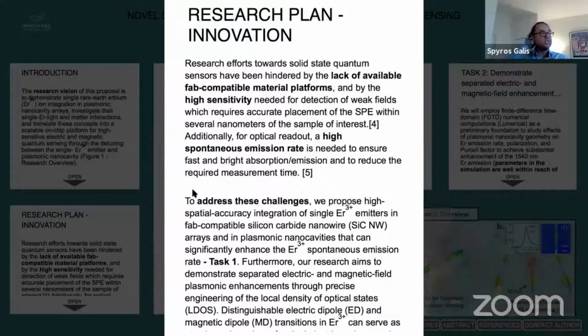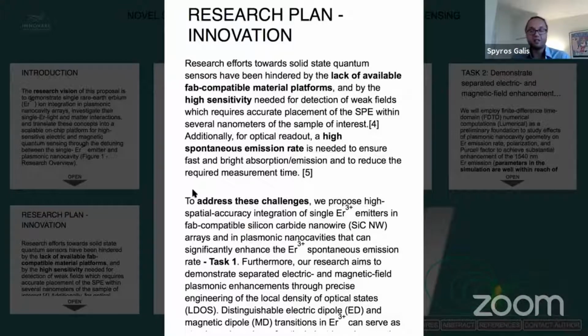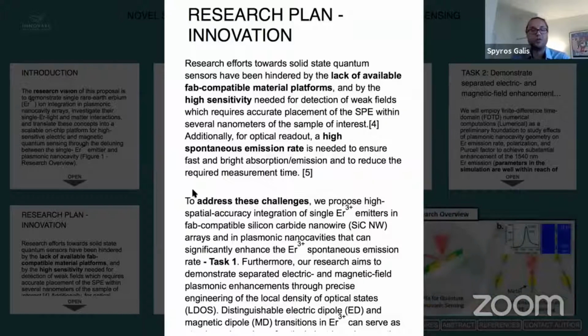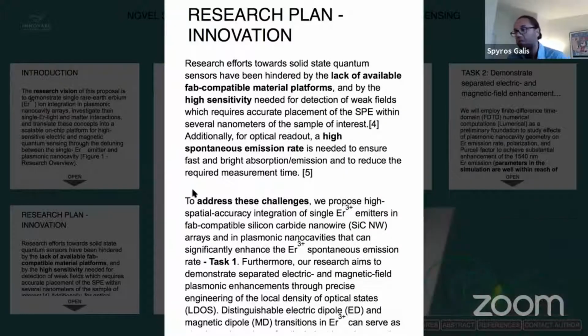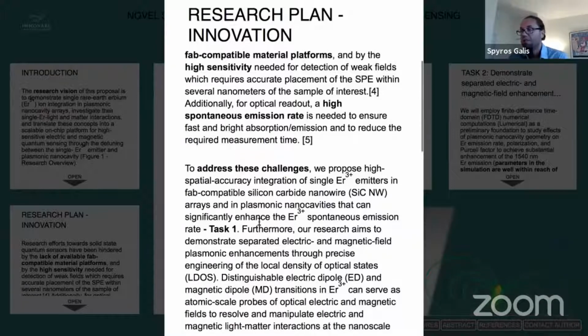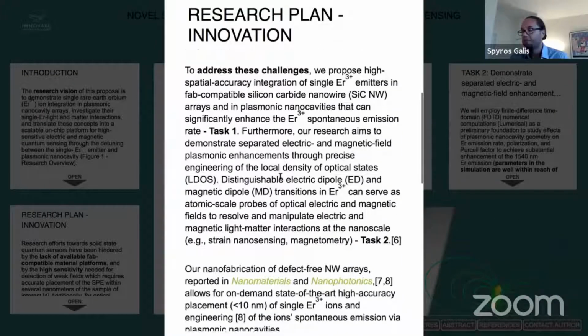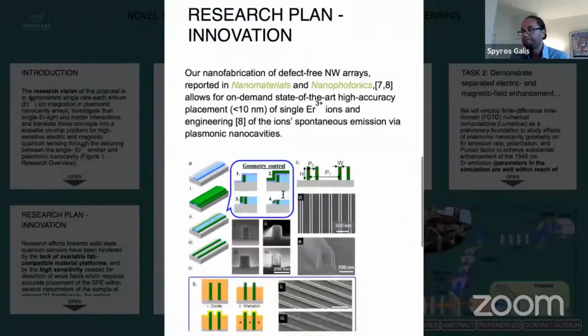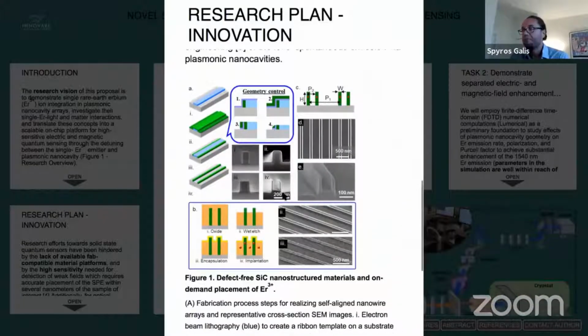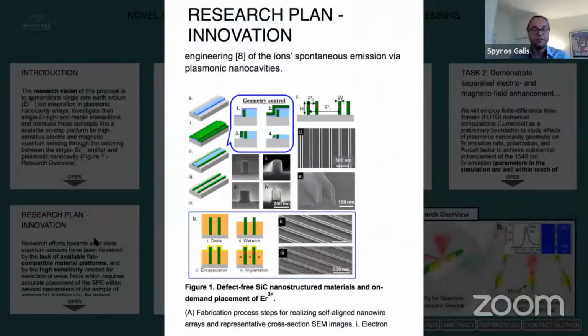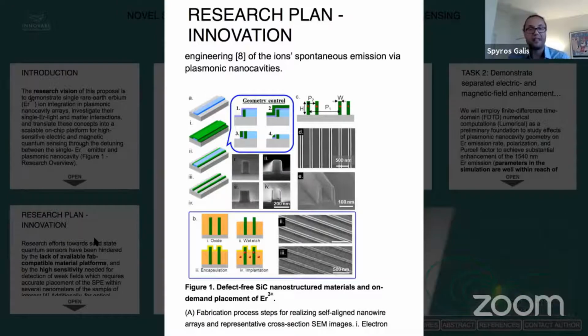So what we propose here in order to address these challenges is a deterministic integration of erbium ions in fab-compatible silicon carbide nanowires, and also into the nano-sized mode volume of plasmonic cavities, which can substantially enhance the spontaneous emission rate of erbium ions. So somebody may say here, okay, this sounds very promising, but what is the innovation that you bring on the table which can make this happen?